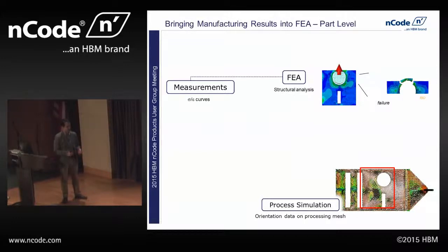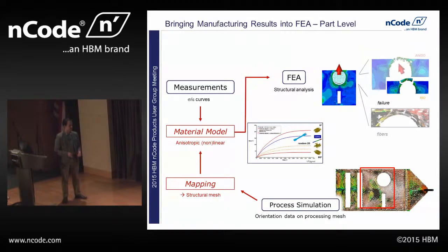And down here in another group, or maybe at your material supplier, you've got some manufacturing simulation happening. And they're doing that to look at, how can I make this part most quickly? How do I reduce warpage and things like that? And so basically what we do with Digimat is we allow you to take these fiber orientation predictions that are happening down here. So what direction are the fibers facing and how much randomness is there? We can bring that along with this Digimat material and couple that into your finite element analysis so that you can get a very accurate prediction of how the material responds from both a stiffness as well as a strength standpoint, and eventually move on to fatigue.